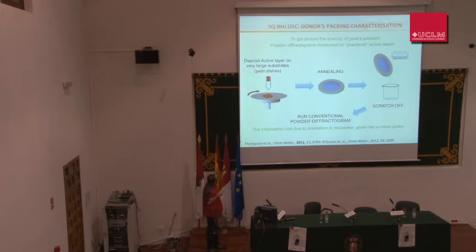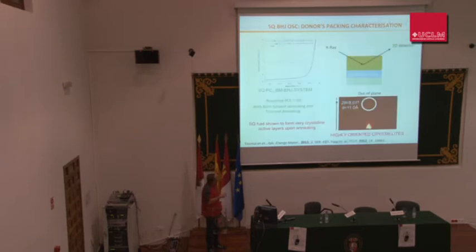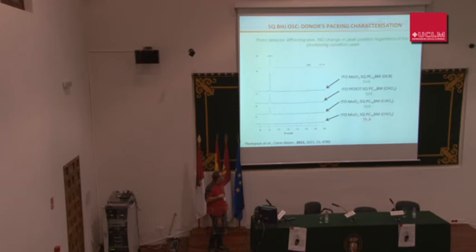We make the spin coating of the film. We anneal in the same conditions as we anneal the films for solar cells, and then we scratch this, and when we have enough powder, we go to the X-ray in powder, and we see these things. A spot tells you that it's highly oriented, it's very crystalline. An arch like that will tell you that your crystals are not very oriented, okay? But they are all in the same plane. So this is the way it is.